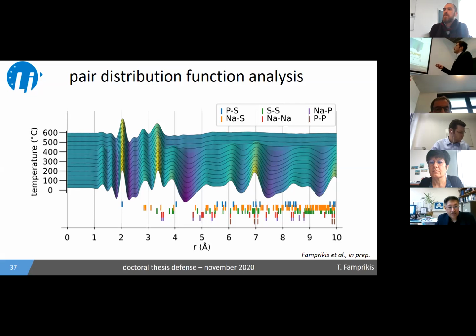Basically, what we see is a complete flattening of the pair distribution function after 4 angstrom. The only 3 peaks that are conserved are the ones linked with the first neighbor interactions, so the PS and the SS, which make up the PS4 anion, and a sodium sulfur distance around 3 angstrom. So this is quite weird in the sense that this flat PDF corresponds to the very sharp Bragg reflections that I showed just before.